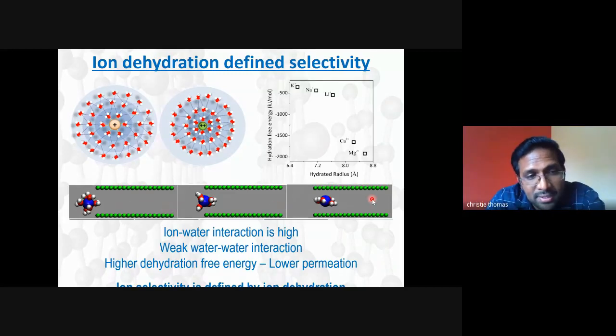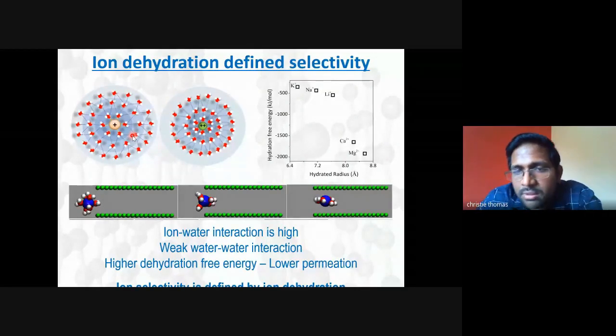But the higher the ion charge, for example Mg2+ compared with Na+, the stronger it attracts water molecules. Accordingly, ions with larger hydration energy are expected to have tougher water shells. The tougher the water shell, the larger the barrier for entry into these nanocapillaries. So the tougher the hydration shell, or the higher the hydration free energy, the more difficult it will be for such an ion to enter this capillary.